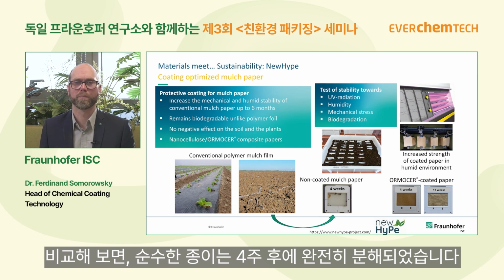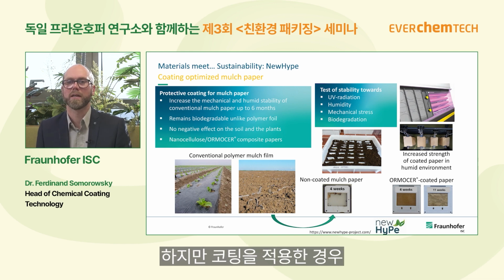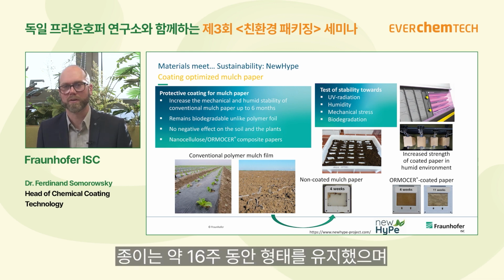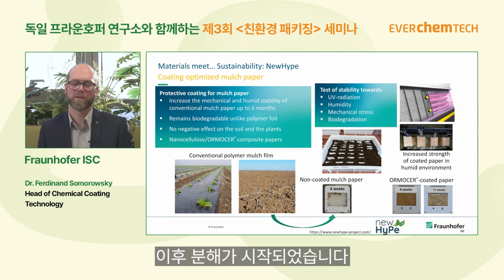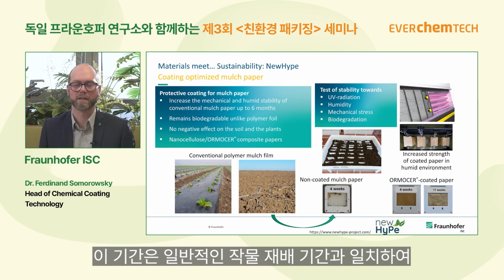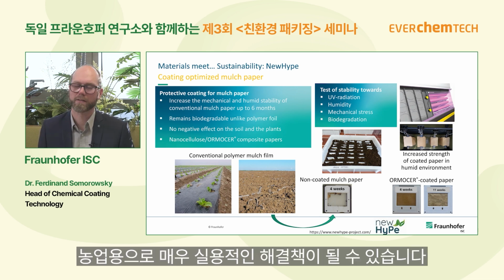And when we look at a pure paper, after 4 weeks the whole paper was degraded, and when we coated, we achieved around 16 weeks of complete paper, and after that the degradation starts, and that is the whole time for a growing period, and it works quite fine to equip the mulch paper with additional functionalities.